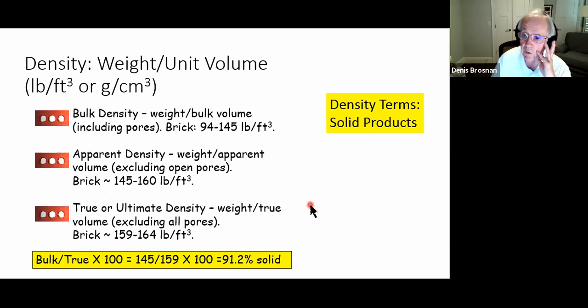So I've given an example for bricks here in each one of these, just because I hung around and worked with bricks quite a lot. But if you take the bulk density and divide it by the true or ultimate density, you'll get the percent solid. So the percent not solid in this case is 8.8%, right? 8.8% porosity in the example that I've given you, total porosity. So those are terms. Generally, you'll have a density goal, and it may be bulk density or it may be true density, but it's going to be one of those that you have in densifying the ceramic.